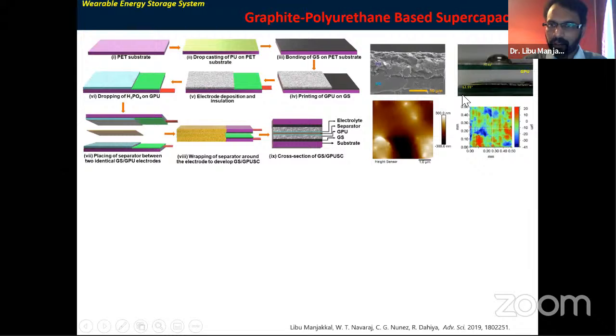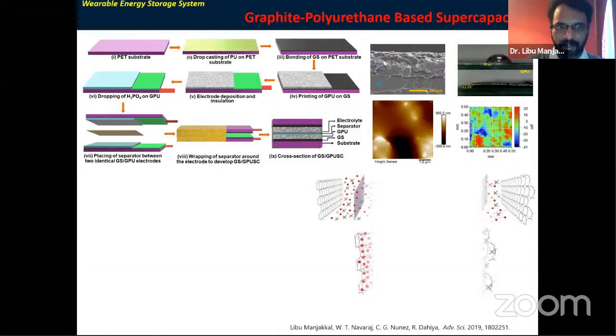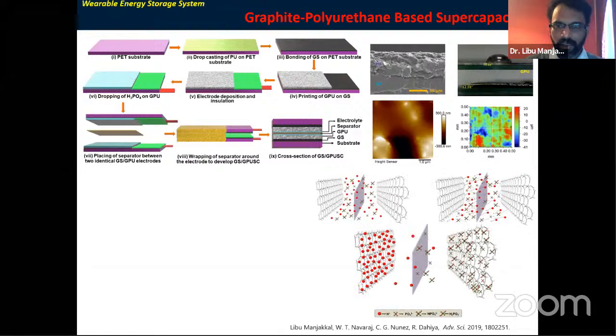You can see here, I dropped a water droplet on top of a graphene sheet, and then on the graphene polyurethane composite, the newly made composite. When I drop it on a normal graphene sheet, the water drop shows a hydrophobic nature. And when I drop it on the graphene polyurethane, it is highly distributed. I used this material for the first time as a supercapacitive electrode material, and we patented this technology. We filed the patent for this application.